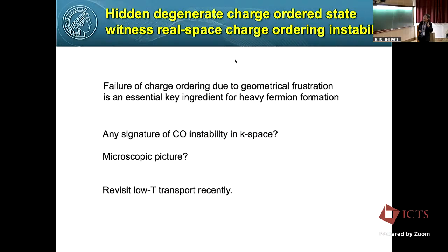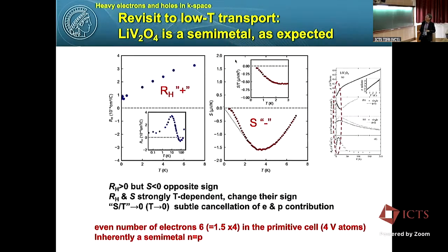Now, the next question we wanted to ask is whether there is any signature of charge ordering instability in k space. And to do so, we revisited low temperature transport, quite recently. The first thing we did was simply measure the Hall effect and the Seebeck effect down to 100 millikelvin. What we found was, well, this is the Hall effect, and this is the Seebeck effect, R plus, S minus. And they are strongly temperature dependent. So apparently, we have both electrons and holes. And in particular, suppression of the Seebeck is quite significant at low temperature. It goes almost to 0. And taking the T-linear coefficient, the T-linear coefficient goes to 0. So there is a very strict cancellation of the electron and hole contributions here.